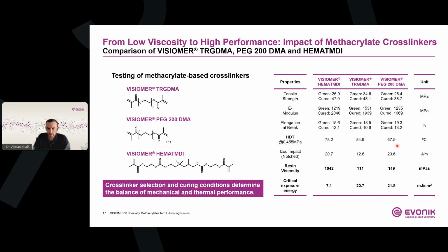And another relevant observation is the curing behavior, which is here indicated by the critical exposure energy. So the minimum light energy that is required to transform the liquid resin into a solid polymer network. And we see that the critical exposure energy is substantially lower for the HEMA TMDI containing formulations than it is for the TRG DMA or the PEG 200 DMA systems. And this demonstrates that changing the crosslinker not only alters the material properties, but also affects the printing process itself.